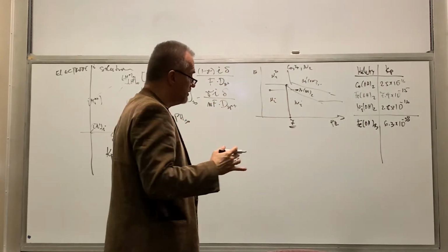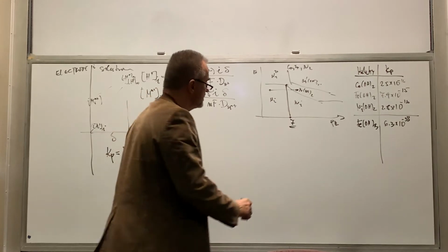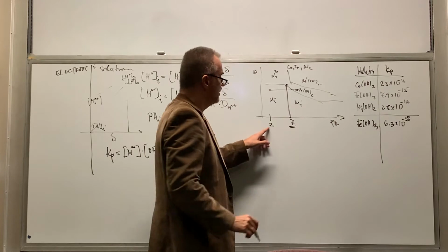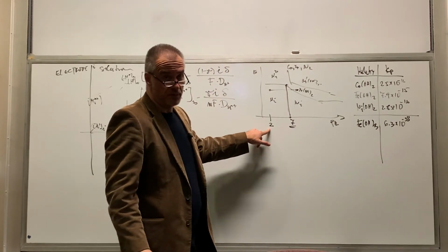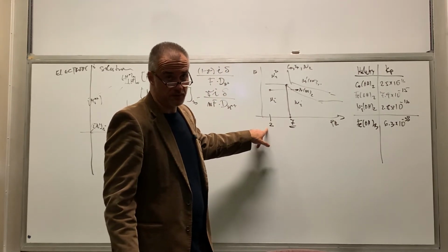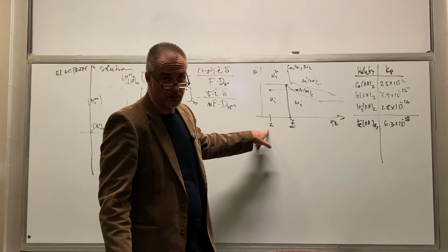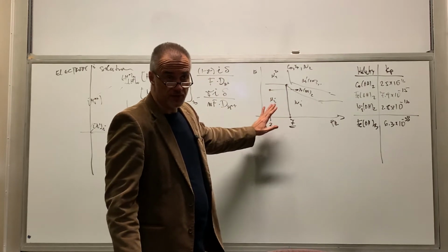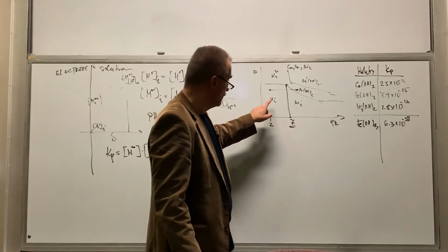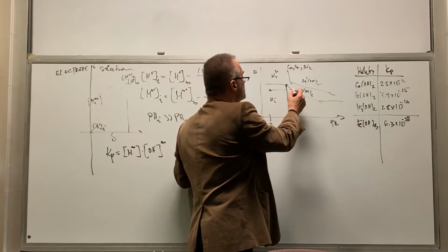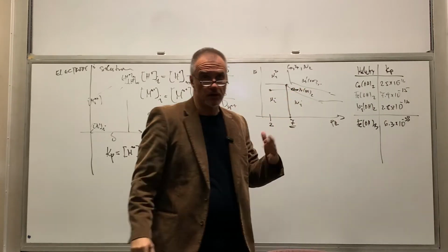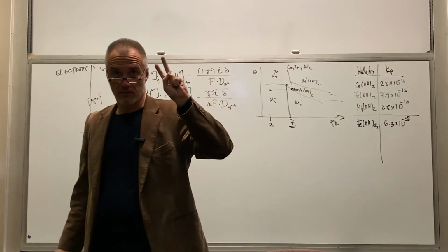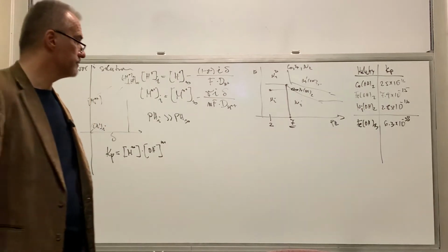And let's say you have some significant depletion. Let's say you're doing the deposition at pH 2, right? Because this is the pH scale. That means you really have to deplete from 10 to the minus 2 molar, which is in the bulk in terms of H plus, to get to 10 to the minus 7. You have to deplete by 5 orders of magnitude to move effectively from this place to the place where you're going to have an issue with hydroxide precipitation when it comes to these 2 divalent hydroxides, right?